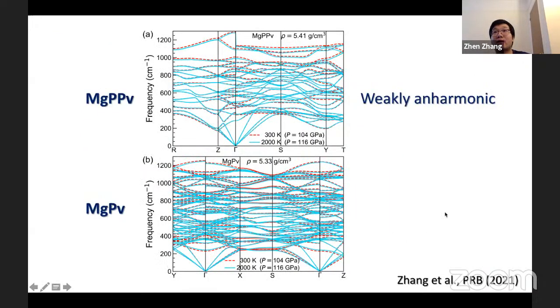Next, I compared the temperature dependence of phonon dispersions of both magnesium post-perovskite and magnesium perovskite at the same PT conditions. It can be seen that the frequency shift of magnesium post-perovskite is also small, meaning that post-perovskite is also weakly anharmonic, and its anharmonicity is comparable to that of magnesium perovskite.